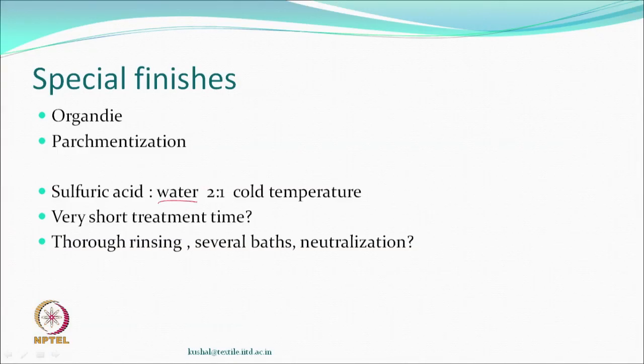So one important thing is, it is quite concentrated. Temperature should be as low as possible. If room temperature is high, you can go for slightly lower temperatures if possible. You treat for a very short time, you're talking about something like seconds, you know, 4 to 5 seconds. That's the kind of treatment that you give. It's pretty concentrated, and so you give this treatment and suddenly you see beautiful things happening.